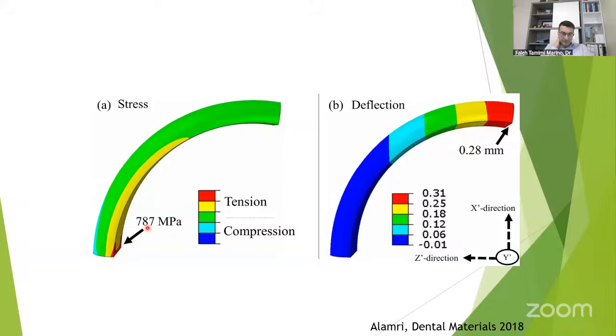The magnitude of the stress here, 787, is higher than the safety limit of cobalt chromium. So this basically means that a circumferential clasp made of cast metal, just by putting it in and out over the years, is going to be subjected to this force, and this force is sufficient to cause deformation over time. So a circumferential clasp has a very big chance of changing over time.